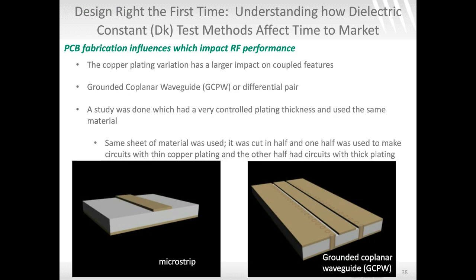And what I did was I used the same sheet of material to minimize material effects. It was a 24 by 18 sheet of 10 mil RO4350B laminate. I cut that sheet in half, and now I have two sheets that are 12x18. One sheet was sent off for circuits to be made using thin copper plating, very little copper. The other sheet was sent off to have the exact same circuits made with thicker copper plating, and I'll show you the numbers here in a second.